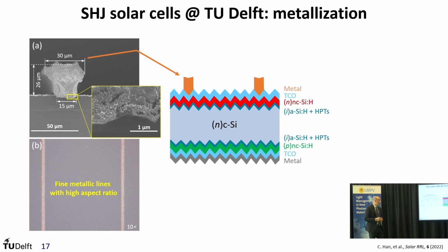Then finally, in order to get charge carriers out of our solar cell when it is connected to an external circuit under illumination, we need to also make some metallization. So in this case, I would like to present our metallization scheme. Typically, for the front side, we use copper plating as our standard baseline nowadays, where essentially we can make very narrow lines, very high aspect ratio, that can give very large opening area for light to be incoupled, as well as a very good conductivity in the bulk of this copper line.